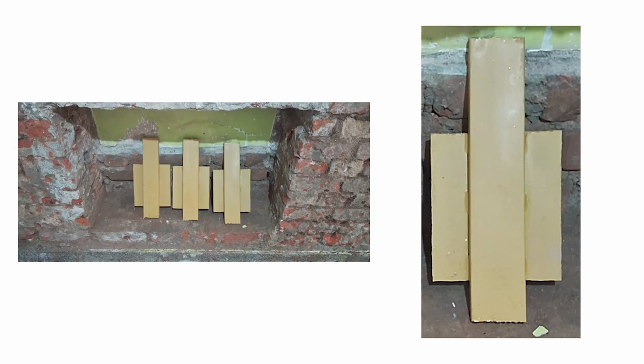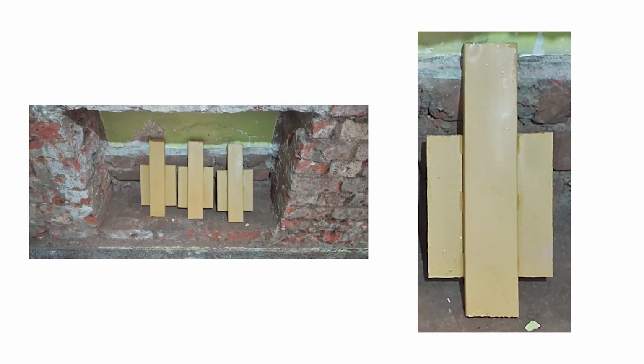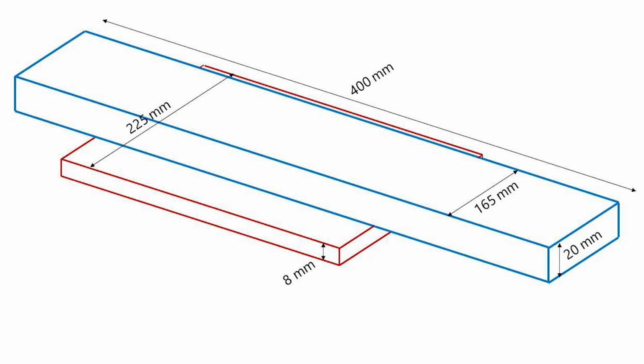The clear span of the beam is about 3 meters. A thin steel plate is welded at the bottom side of the steel block at a defined configuration. Reason, I will come to soon. A composite block is fabricated. It also enhances the bearing area of the block on the wall. The composite is painted thoroughly with primer to reduce corrosion effect. This modified block is now made ready for erection. Overall size is 20 mm thick, 225 mm width and 400 mm depth. Here depth means inside the wall.